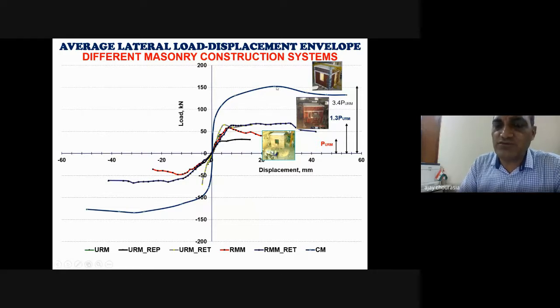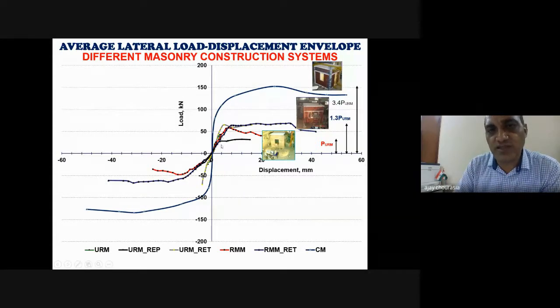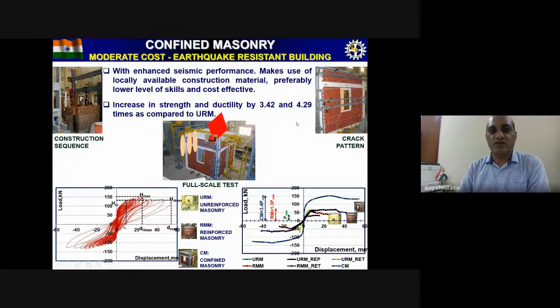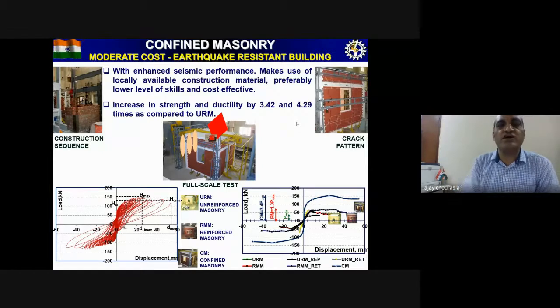It showed that confined masonry resisted 152 kilonewton lateral load and a maximum displacement of around 54. In contrast, the unreinforced masonry had a maximum load resistance of hardly 32 kilonewton and a displacement of 10. Similarly, the initial stiffness was also quite large as compared with the unreinforced masonry and reinforced masonry. In short, when we compare the results, it gives confidence that confined masonry is a promising technology, which enhances the seismic performance by small interventions.